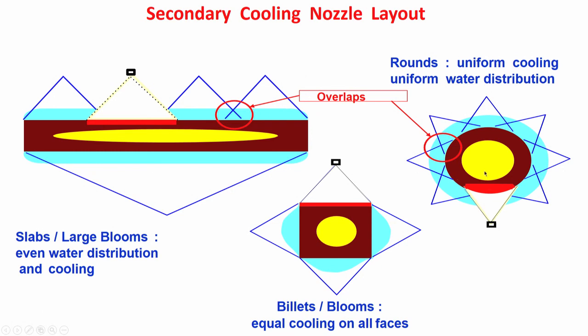Other nozzles 1, 2, 3, 4, 5, all are functioning. This is not functioning. So, what is happening? This area, you see, that blue indicates the water cooling. So, no water presence is there, because it is choked, water is not falling on the round surface. So, what is the problem? The problem is, compared to the adjacent areas of the round, this particular area where there is no water falling,